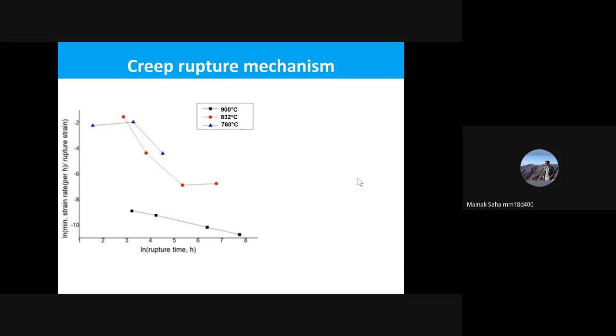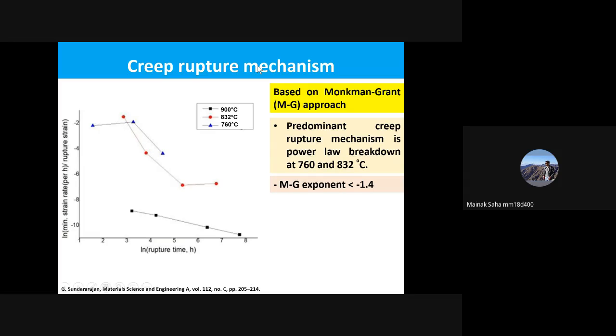But there is another phenomenon that needs to be addressed, and that is the creep rupture mechanism. The creep rupture mechanism can be addressed using another mathematical approach, the Monkman-Grant approach. Based on that approach, what we can say from this particular plot is that the predominant creep rupture mechanism is a power law breakdown at 760 to 832 degrees.